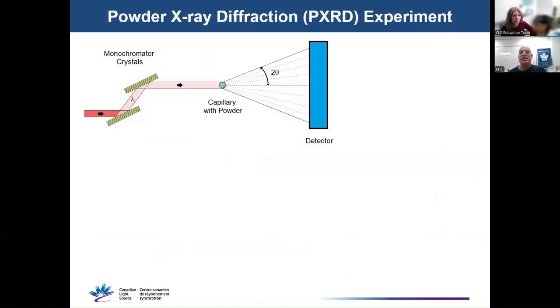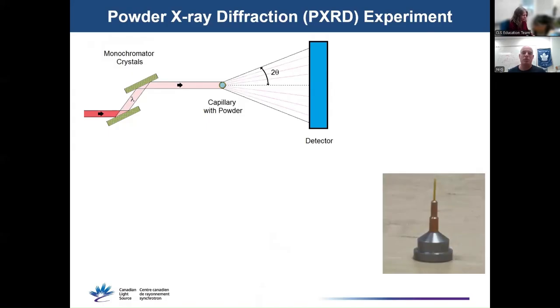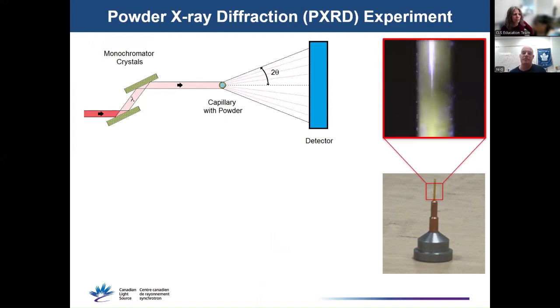So the previous three examples illustrated structures solved from single crystal diffraction. But sometimes you don't have a large single crystal. You just have a fine powder with millions of tiny crystals. But we can perform diffraction on powders as well. Instead of a loop with a single crystal on our sample base, for powder diffraction, we have a small capillary tube that's filled with powder.